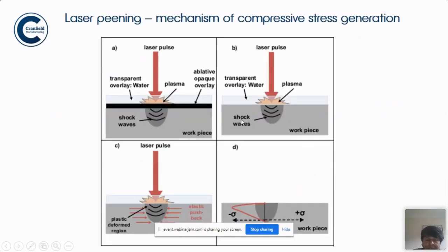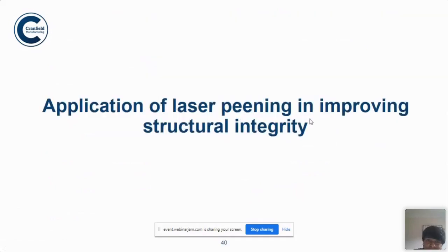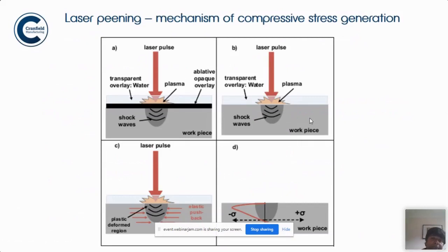Now we'll talk a little bit on the structural integrity by laser peening process. We have a laser which can peen, and this is the peening process in a schematic. You can see on picture A, there is a laser pulse which comes and hits the surface of the metal, and then there is a transparent overlay of water here. Sometimes people use what we call an ablative layer. Sometimes people do not use an ablative layer. When you don't use it, the metal itself will vaporize. You bring this to a very high power density, in the tune of say 4 gigawatt per centimeter square for aluminium. Then you heat it very hard, the aluminium vaporizes, it will try to escape the surface, but this water will prevent it from escaping.